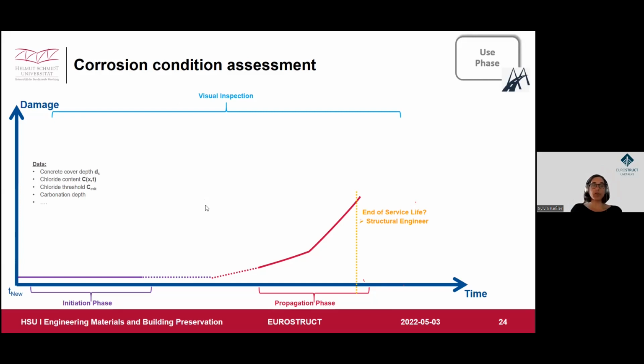Always the concrete cover depth and the chloride content. So you make a chloride profile. You can also measure on a structure the critical chloride threshold. It is very uncommon because the procedure is quite new, but the procedure is now possible. And the carbonation depth. These are the most important parameters, and you have to destroy your structure very slightly. You need to at least drill a borehole to get the powder for the chloride profiles.